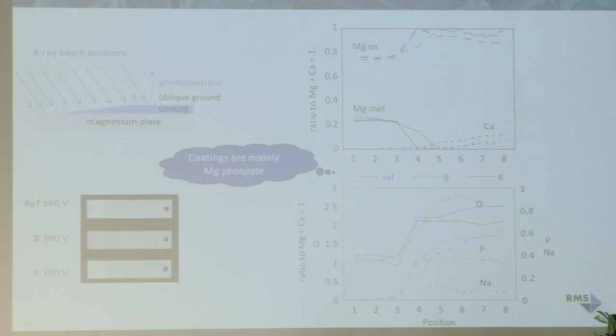We also try to characterize them with X-ray photoelectron spectroscopy, so XPS. For this, we grinded the magnesium plate so that here, position 1, we are on the base metal, and then we go across the coating. Position 8 would be here on top of the coating. What you see is that here, position 1, we still have metallic magnesium. We also have oxidized form of magnesium. But then on top of the coating, there is no metallic magnesium anymore.